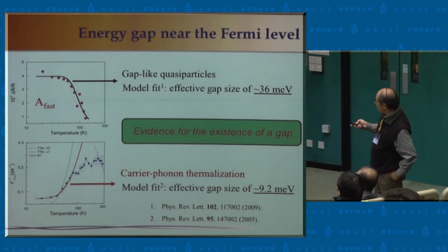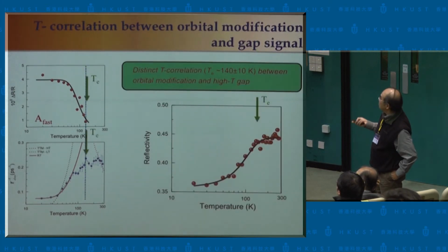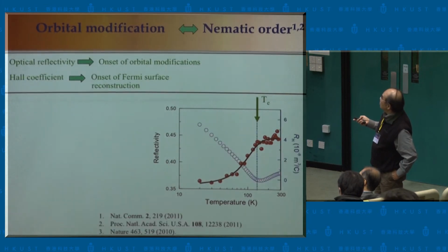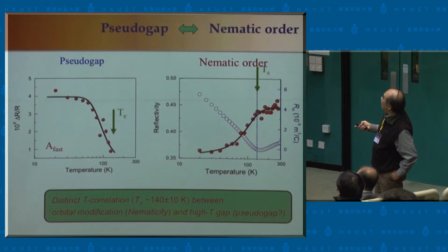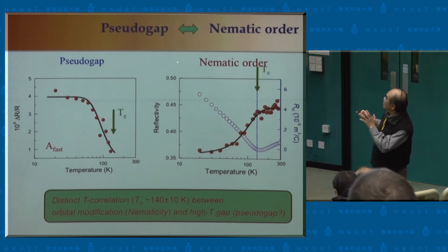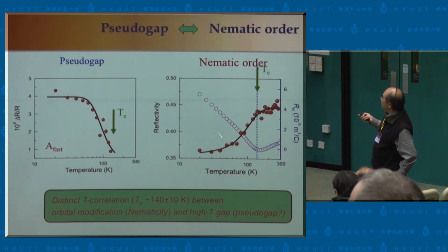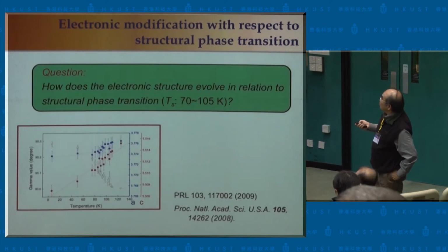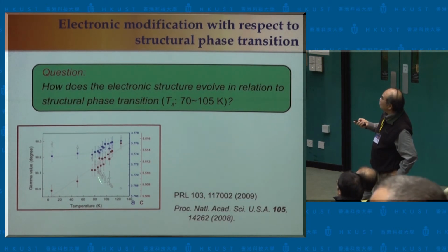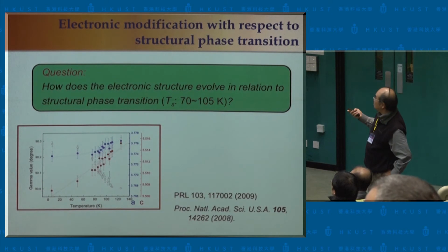So, evidence for the existence of a gap. And that gap clearly is associated with the distinct correlation with this orbital modification. That also clearly can be associated with the thermal Hall effect I just showed you earlier. All right, and those tell us there might be some kind of pseudogap associated with this nematic order.